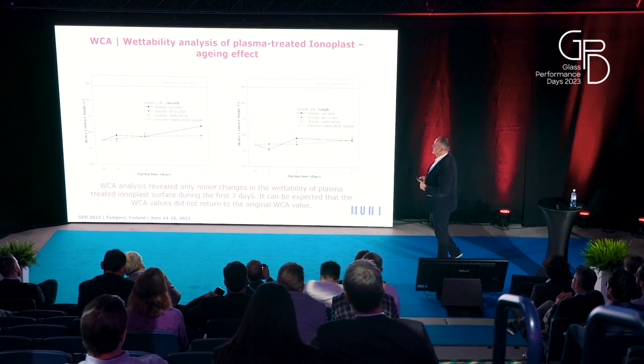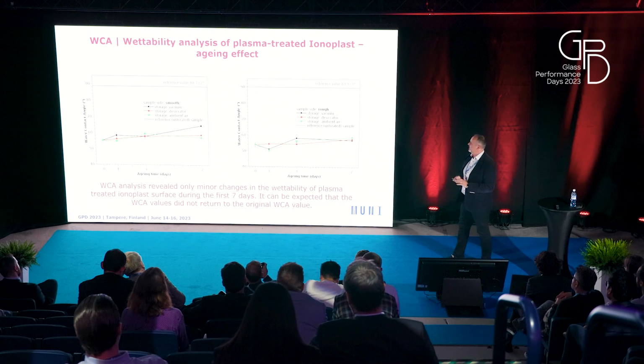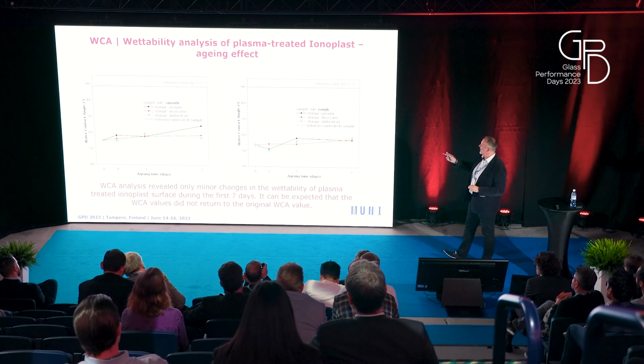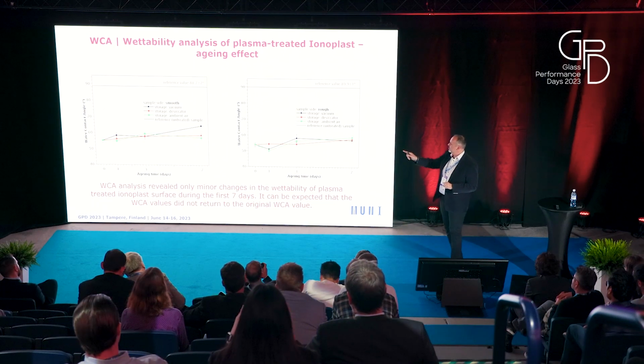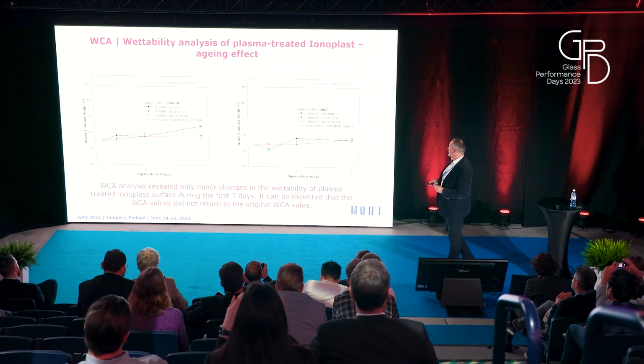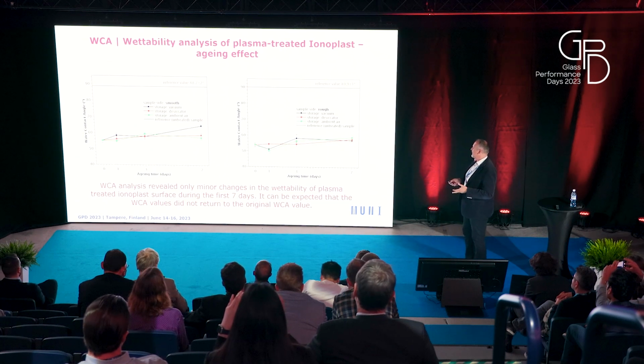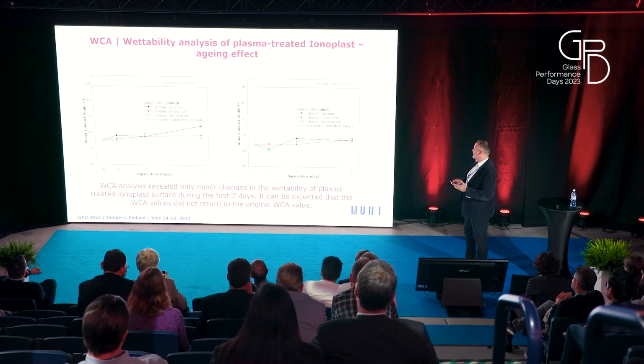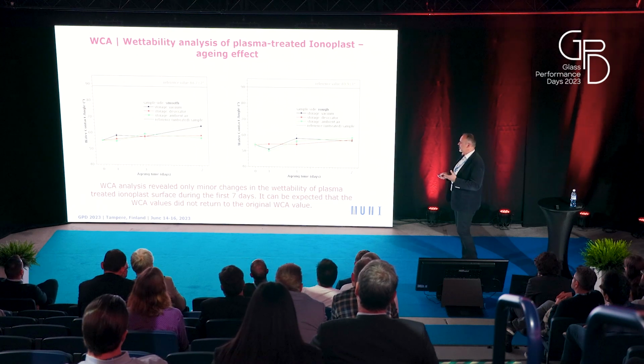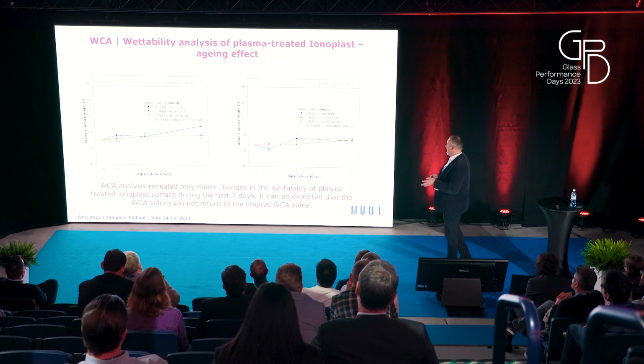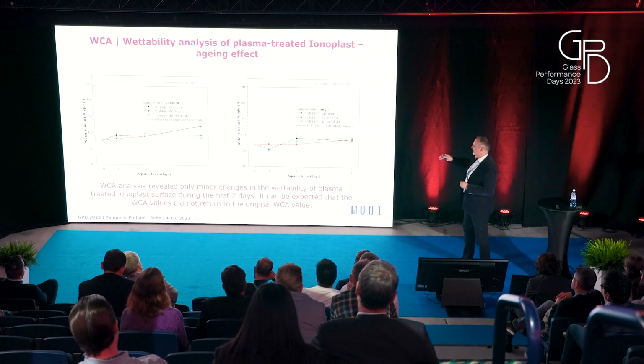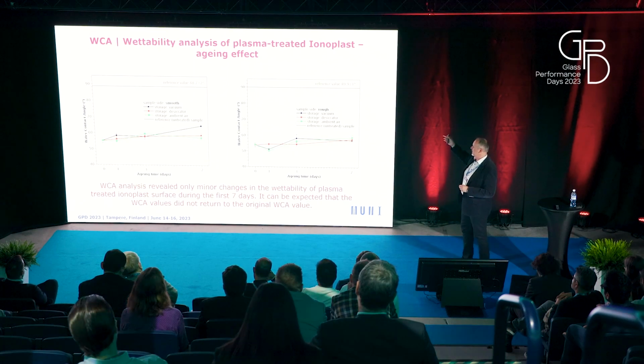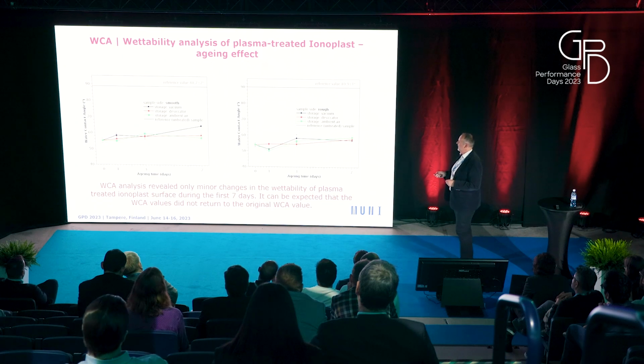The stability of the treatment is also sometimes questioned, and we investigated the stability over a duration of 1 week. As you can see, during these first 7 days, we didn't observe any major changes in the wettability, and we also didn't expect a return of this value to the value of the reference sample.